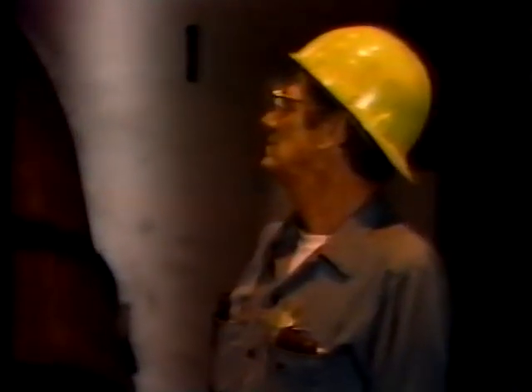Here the hardness of the coil is removed by heating it for 3 to 4 days in portable cylindrical furnaces that reach 1300 degrees Fahrenheit. The steel is gradually brought to the required temperature in the first 30 hours, then cooled for the remaining 50 to 72 hours. Upon being removed from the annealing furnaces, the steel is in a state referred to as dead soft. It then must cool for an additional 2 to 4 days to reach 100 degrees or less. Now it's ready for further processing.